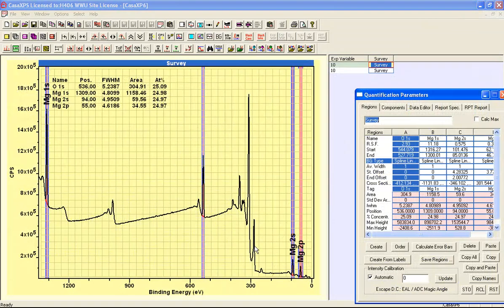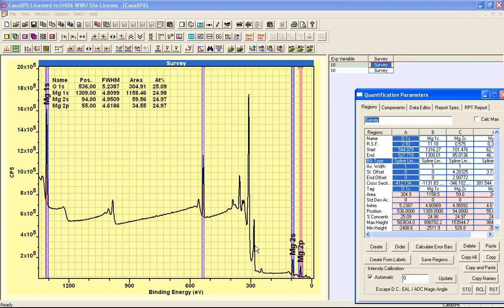So the measurement was performed not on pure magnesium oxide, but a combination of magnesium oxide and carbon black. And as a result, no charge compensation was used, and the carbon is in spatially distinct places from the magnesium oxide. So we can compare the magnesium oxide results with a degree of confidence that we do not have a significant amount of contamination here.